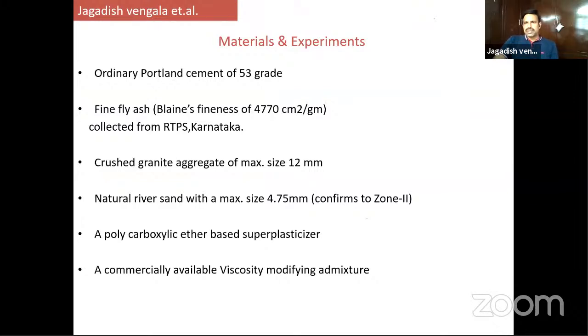So when we worked in 2002, these are some of the experiments I would like to mention. We used OPC 53 grade, and during that time I was in Bangalore working for Tata Steel Research Foundation, India, wherein we brought Raichur Thermal Power Station fly ash, with Blaine's fineness of 4,770 square centimeters per gram. We used 12 mm down, and river sand. At that time natural river sand was available. Now in Bangalore, most of the sites are using manufactured sand, crusher fines. And we used polycarboxylate based superplasticizers and VMA.